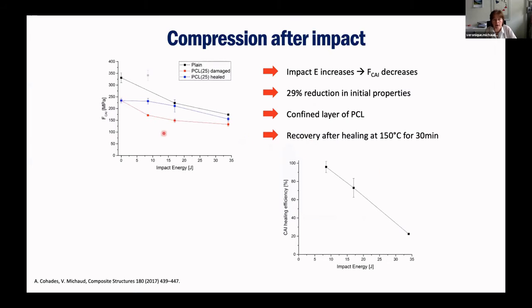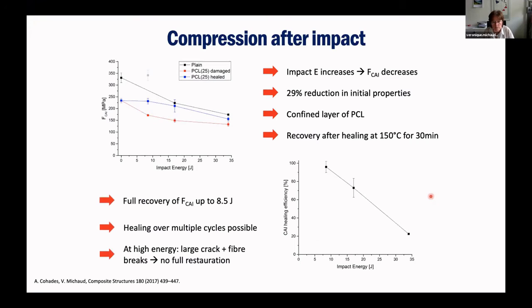we had this blue curve here, which shows that, okay, it's not as great as the plain material, which was not great in that case, but we have a recovery. And we see that the healing efficiency in compression after impact is almost 100% compared to, we have almost the same value as the one without impact. So we recover the energy here. But then if we go a bit higher, then we lose, of course, because we start to damage the fibers.